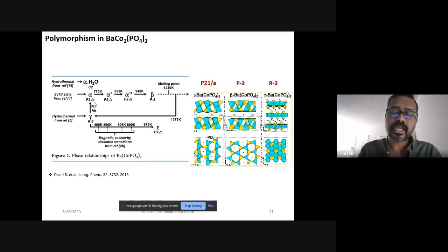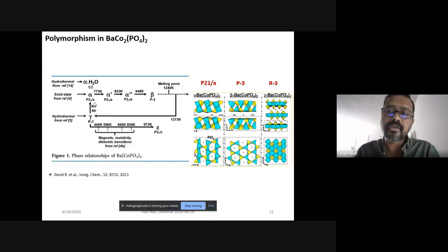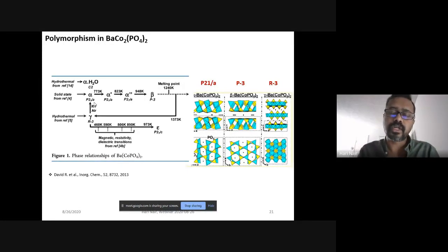Now, it is important to get the correct phase of this compound. Why? Because this compound has polymorphism, which means that depending on how you prepare it, you might end up getting a totally different crystal structure. Whereas we are interested in the gamma phase only, which is the R-3 space group on the right-hand side of the image. So we want only that and not the other two on the left. There is a special way of controlling it, and that's what we did to avoid having the other two phases and get the gamma phase, which is the R-3 space group structure.